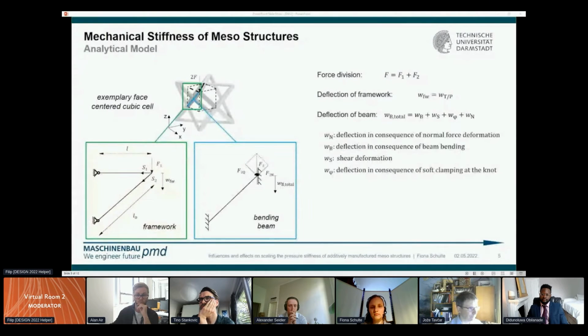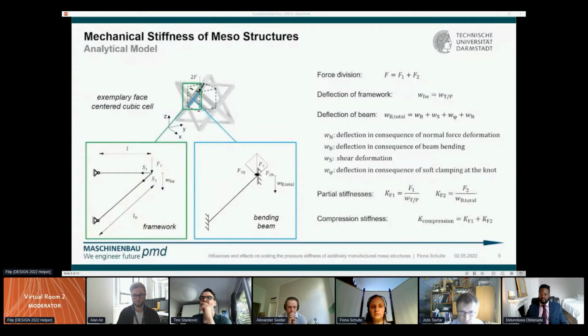The second path is modeled as a bending beam following the bending line with a double-sided clamping, additionally considering shear because the struts are stocky, and a compression arising through the hindrance of deflection at the knot. Furthermore, the knot areas correspond to a soft clamping instead of a fixed clamping, which is regarded in the bending line, which are considered here by an additional deflection. The partial stiffnesses of both load paths are summed up to the total compression stiffness of the cell.